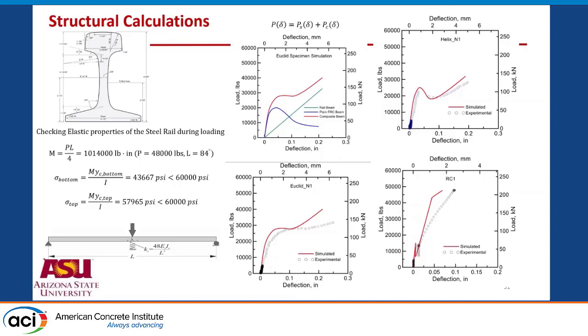It allows us now to add the response of the rail, which remains purely elastic, to the response of the sample, whether you have rebar or fiber reinforced concrete. Add these two up, and you get the responses that we measured in the experiment's load deflection. These are shown for the fibers and for the reinforced concrete. Basically, the blue curve changes from one case to the other, and we can see how much it goes up to the yielding of the rebar.